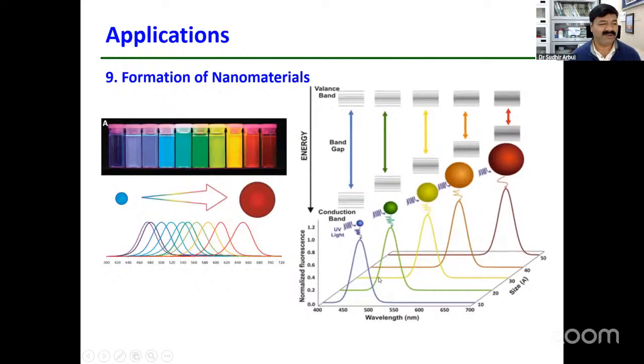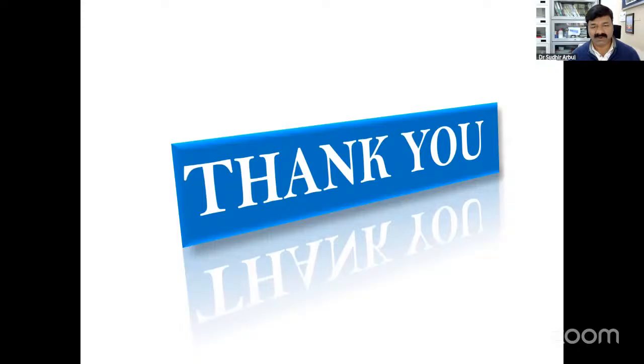Another thing I have already discussed is that the formation of nanomaterials changes the band gap of the material. So this is the famous cadmium telluride material. And see this, the bulk material. If you change this material from bulk to nano, see how the change in the band gap appears, and it covers the whole solar spectrum from 400 to 700 nanometer. This is the beauty of nanotechnology. Your material is the same cadmium telluride, but you can make this material in such a way that it can absorb the whole solar spectrum. Okay, that's all about UV-visible spectroscopy.